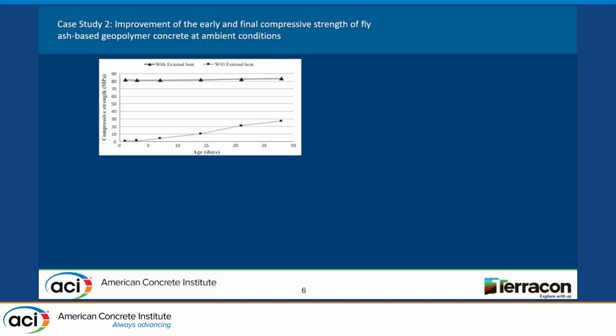You can see here the same concrete. I just didn't use external heat for 24 hours, and the compressive strength is really reduced drastically from around 80 at 28 days down to really low, there is almost no compressive strength at one day. And at 28 days, you can see here is around 30 megapascal, which is around 4,000 psi. But the early compressive strength is not really good, so it's not really useful. So we need to have a solution for that.